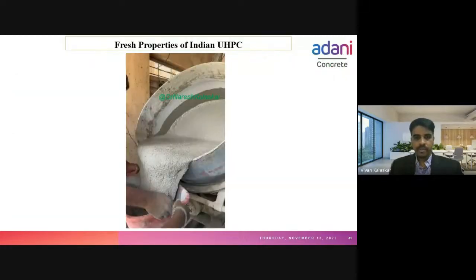In this M150, we got 164.06 MPa compressive strength. So in this study, I have stopped at M150. M150 standard deviation is 7.82. Here is a small video of the mix, you can see how the fresh properties of this mix are.